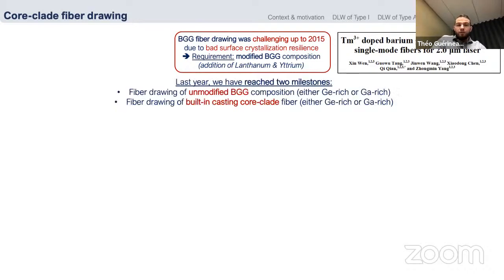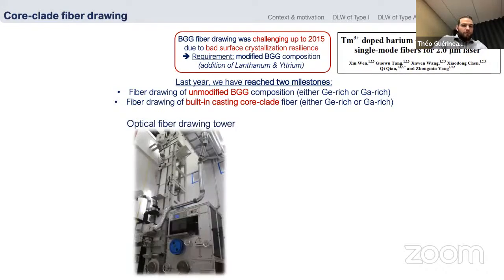But last year, at COPL, we reached 2 milestones actually. The first one is to fiber draw unmodified BGG composition, either if it's rich in germanium, or rich in gallium, and also to fiber draw built-in casting core-clad fiber, also in the 2 type of regime. So here is the optical fiber that we use.